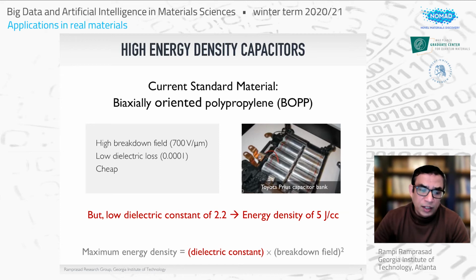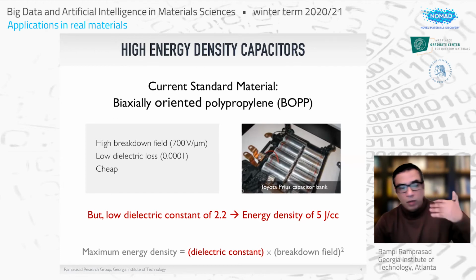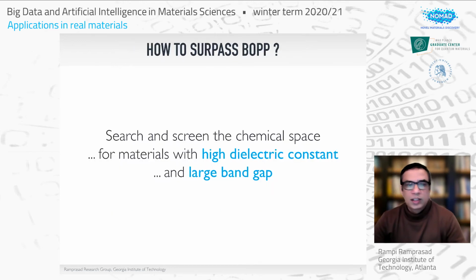The maximum energy density, the maximum energy you can store in a linear dielectric material, is given by this very simple looking formula, right? Dielectric constant times the square of the highest electric field the material can withstand, right? So basically this means that if you want to come up with something that is better than polypropylene, you need to find something that has a higher dielectric constant and preferably a higher breakdown field than that of polypropylene. Easier said than done. But anyway, here is the screening criteria in a slightly different form. We want to search and screen the chemical space of polymers for materials with high dielectric constant and large band gap.